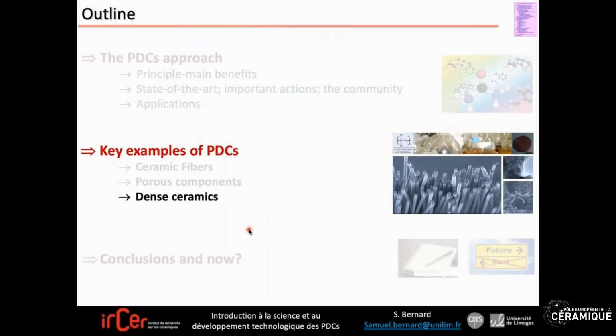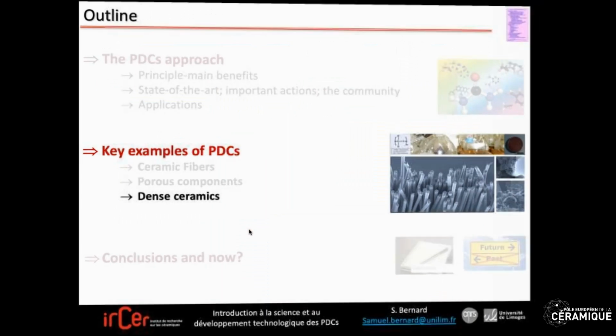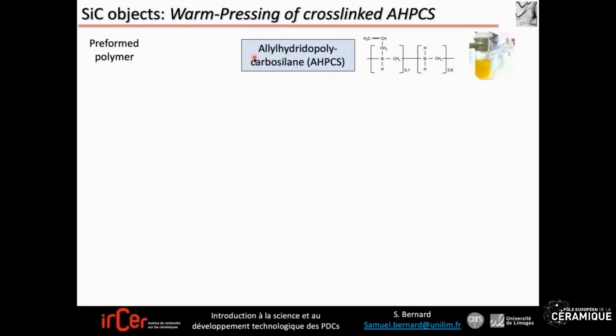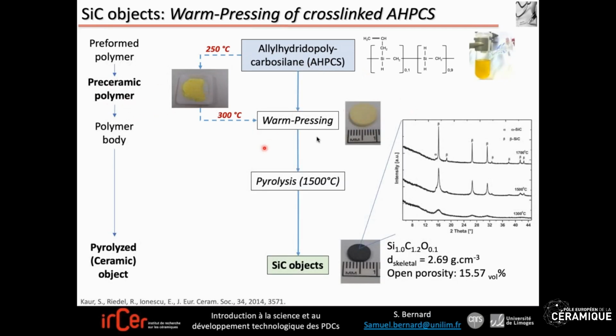The last example, the design of dense ceramics. So we start again with a preformed polymer, silicon carbide precursor. We don't care about the name, but this is a commercially available precursor. This precursor is thermally crosslinked to form your preceramic polymer. Shaping, warm pressing. The pressing is achieved at 300 degrees C, and pyrolysis at 1500 degrees C to form your PDCs object, here silicon carbide, because we use the silicon carbide preformed polymer. So you can again recognize the different steps of the PDCs process.